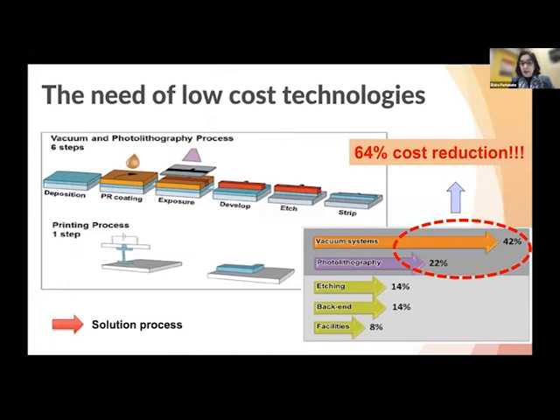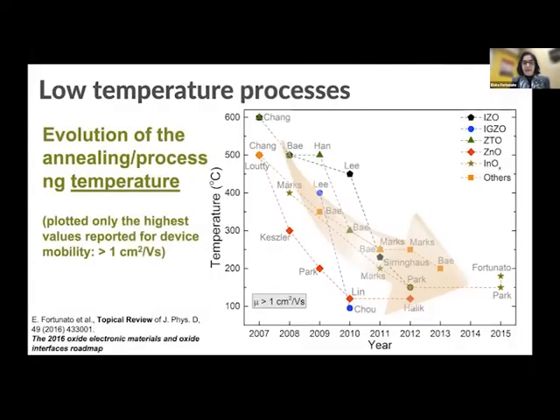In terms of technologies, of course, we are working a lot on printing technologies. And here I have an example of a conventional microelectronic process using photolithography. For example, just to pattern a single line using the conventional process, you need to have 6 steps. And if you are using printing, you just need to have 1. Of course, we have a tremendous cost reduction of more than 64%. We don't use vacuum systems. We don't use photolithography, photoresist, and we are not generating waste by using these printing technologies.